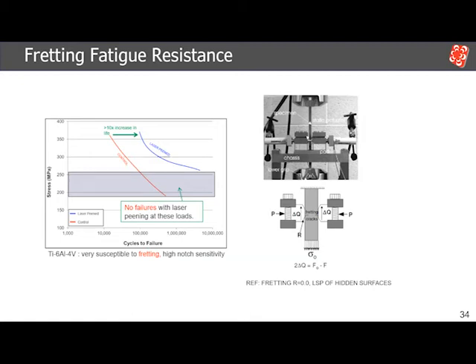a later time. In a very similar manner, you're creating compressive stresses by laser peening. These compressive stresses counteract the applied tensile stresses from this fretting fatigue. And you can see that laser peening is able to generate a life improvement up to 10 times. But moreover, because you're generating compressive stresses, you're generating an area in this curve that failure is no longer generated. It's kind of a knee curve, similar to a lot of the SN curves for different materials.